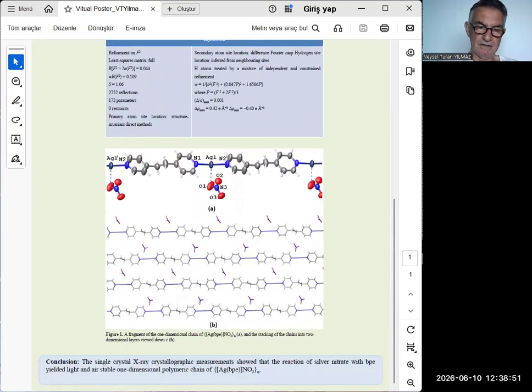As shown in Figure 1a, the silver ions were bridged by 1,2-bis(4-pyridyl)ethane ligands through the pyridine nitrogens, and this forms a one-dimensional coordination polymer running along the crystallographic axis a. Yes, you can see here a part of the chain.